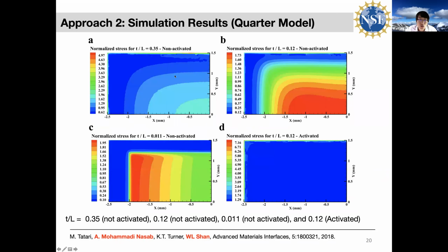So we also did finite element simulation. This is the quarter model, and this is the center of the interface. You can see that when we don't do activation, cases A, B, and C, there's a high stress region in the center. But if we activate the region in the center, there will be nothing there because everything's soft. So you're only going to have stress concentration at the edge, and this will promote edge cracks, whereas all these will be center cracks. And there's a shift of the center crack location.